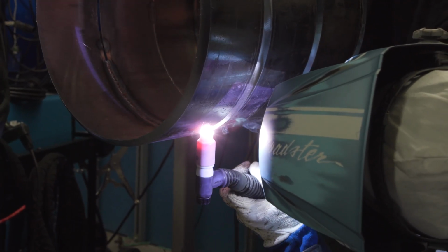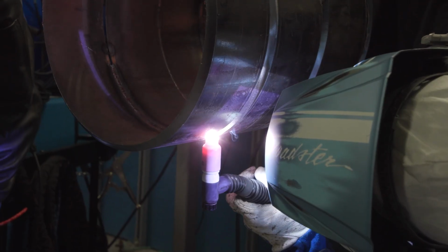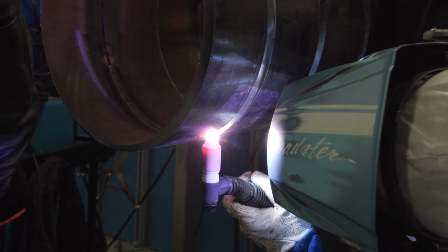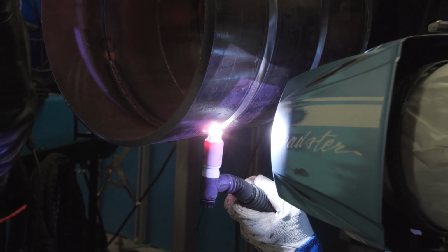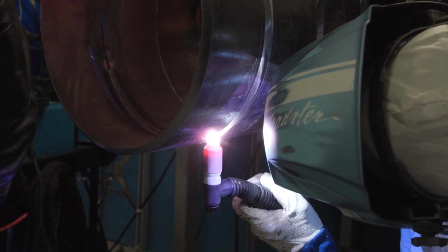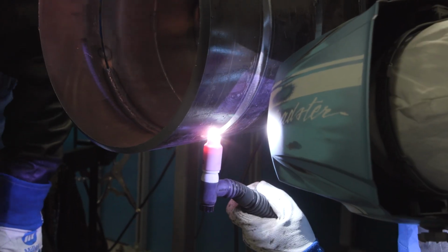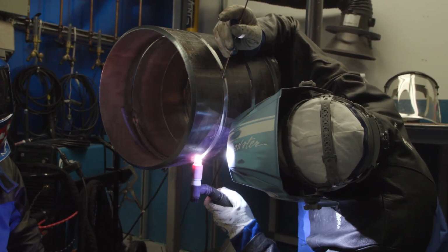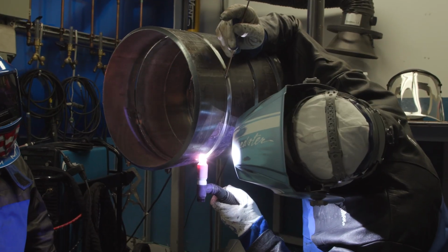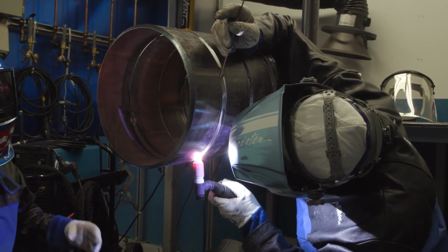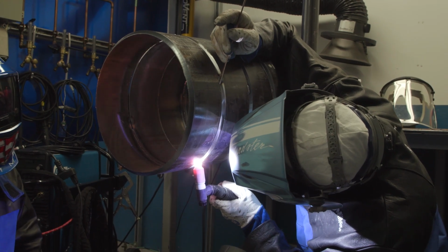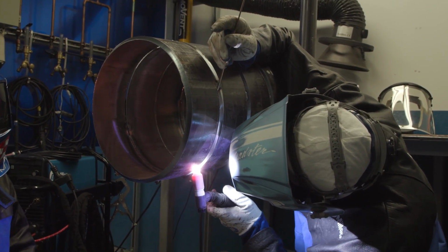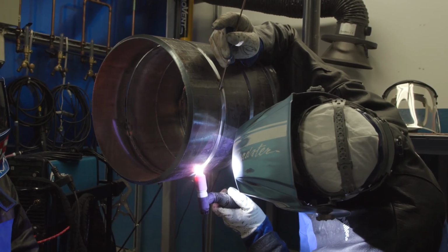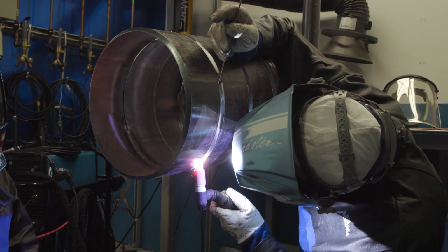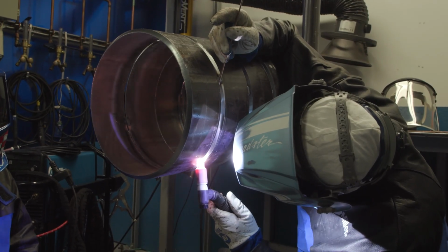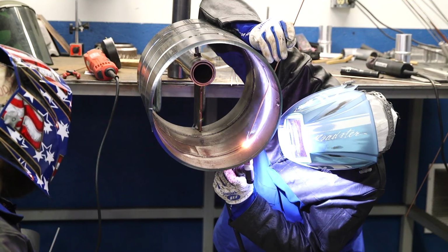Now with carbon steel and 70S6, we use a constant feed technique. When me and Travis were tag teaming 304H, so 36 inch, 24, and 46, some weird sizes on that job actually, that filler wire was a custom wire for 304H, an ER 16-8-2. And with that stainless alloy, there was a little bit of sluggishness to it. So our technique, we adjusted to be a dip and keyhole. And backfeeding like this, you wash out, eat your bevels away, and add a little bit of metal to the back of the puddle. Wash your bevels away, develop a tiny keyhole, add filler to the back.